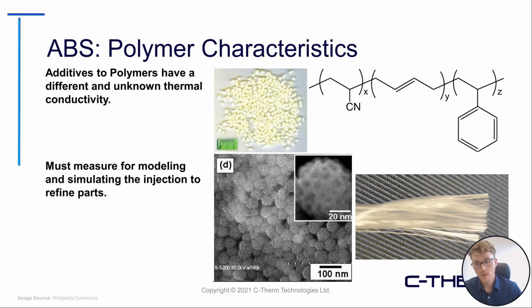Now, with the advent of adding polymer or microspheres, nanoparticles to desirably change the thermal conductivity, or to change some of the mechanical properties of polymers with the use of glass fiber and other fillers, this shifts the thermal conductivity of the final product itself, meaning that all these computational values that are completed on just the bulk polymer itself are not representative of the material that's being formulated for injected materials. So it highlights the importance of being able to measure whatever material you're going to be injecting into these molds, be it composite or bulk polymers, at the temperature and pressures of interest.